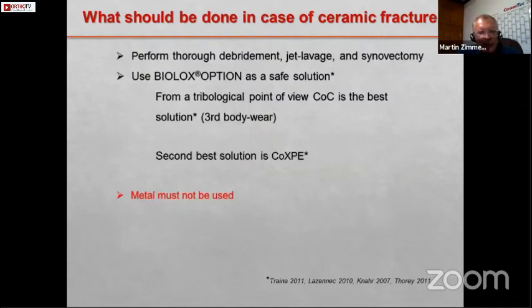That means if you use afterwards a combination of a metallic ball head against a polyethylene, for instance, with the presence of these ceramic particles, you are creating a grinding machine and you create really a problem. And I will show you after a lot of publications speaking about that. So the metal head must absolutely not be used when you have a replacement after a ceramic fracture.